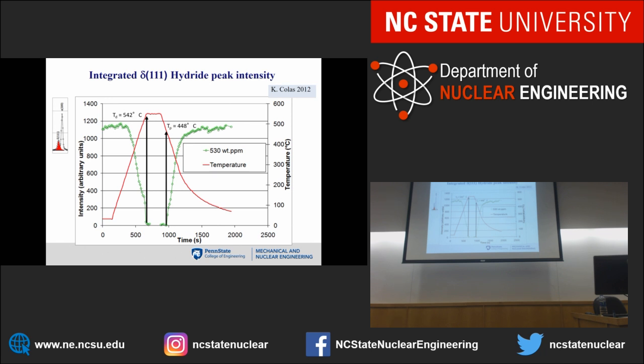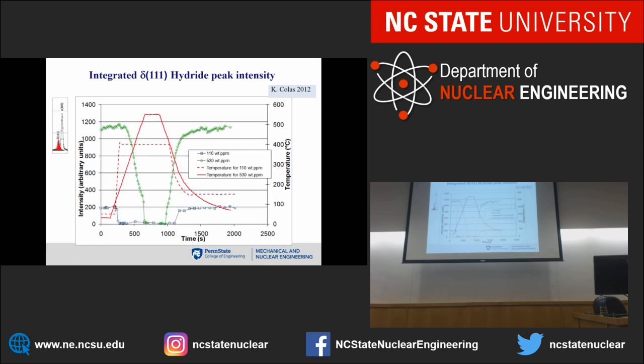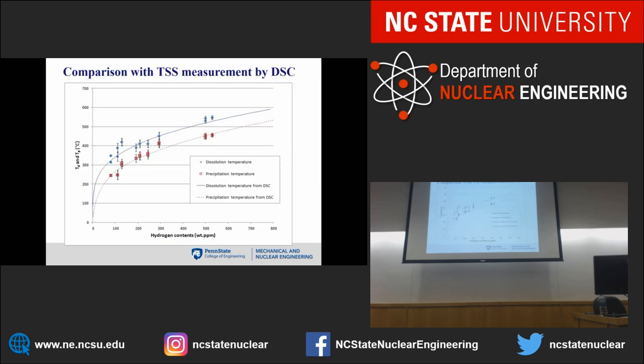And I can do that for several hydride contents. Here's another one, much lower one. I took it up in temperature, get it down, and here my diffracted intensity goes to 0, and then goes up again. And I got another one that says it's 390 and 248, okay? So now I have done this many times. I can now plot it against those curves, except that they are flipped, right? And you can see that the points agree very well with the differential scanning calorimetry for precipitation and for dissolution, okay?